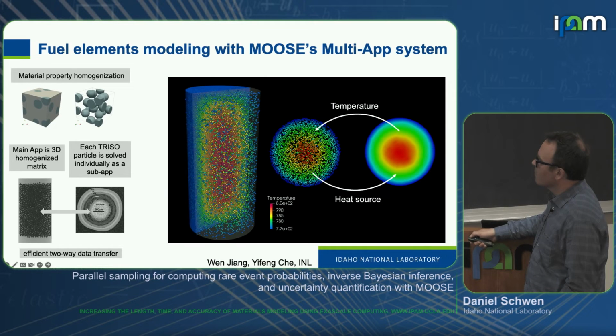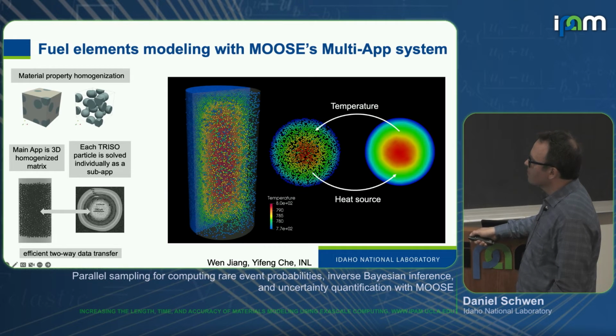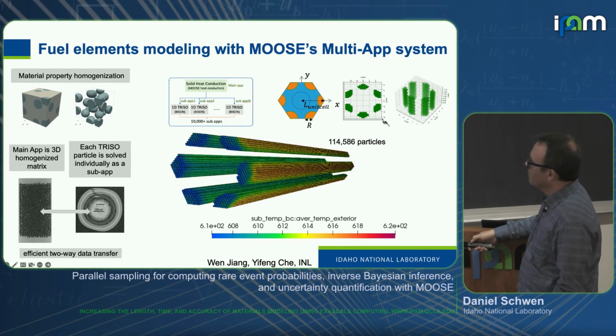can use the multi-app algorithm to simulate now a TRISO fuel compact. So this is like this slug of graphitic material, pyrolytic carbon, with all those TRISO particles embedded. And we can run 1D simulations for the thermal transport and the neutronics for all these TRISO particles, and every TRISO particle is a little heat source in this compact. And then we have a homogenized approach for the master or main application. Again, one big main application for the thermal transport and hundreds and thousands of the TRISO particle simulations. And that has two-way coupling, so to get thermal feedback on the particles.